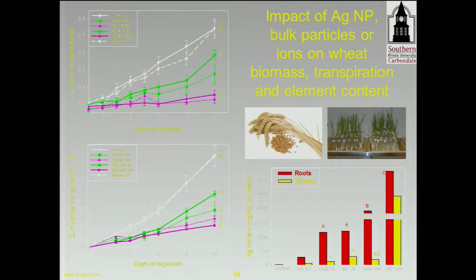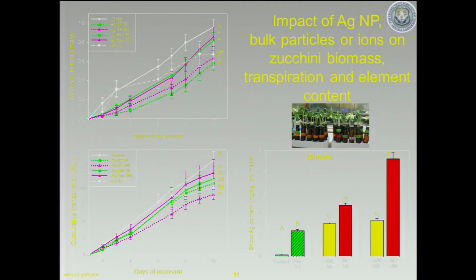We tried to make the nanoparticles in suspension, because if you put the nanoparticles in the water and then at the end they all settle down at the bottom, you come to the conclusion that it's not toxic. It's not a correct experiment, because the nanoparticles haven't gone into the plants, and you can't keep sonicating all the time. That would actually have a harmful effect on the plants, and the plants would not grow as much. So, that is when we tried to use SDS, and we found that everything was coming out toxic. Later we found out the toxicity was caused by SDS and not by the nanoparticles. So, this is the impact on the shoot.